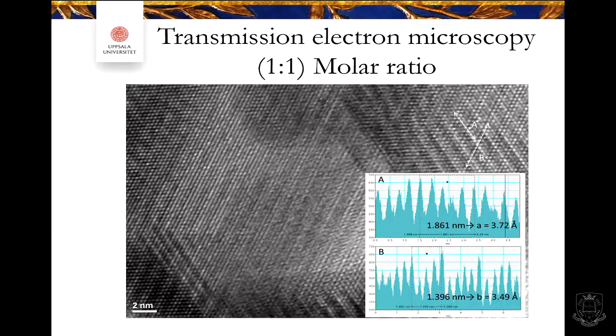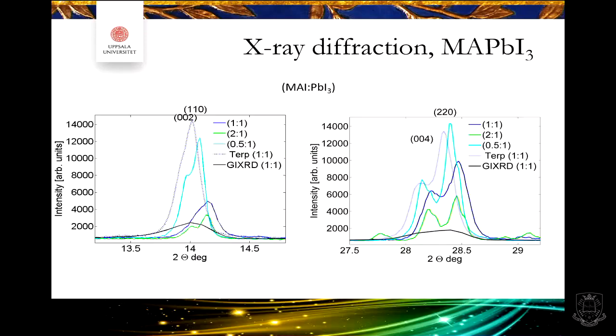This was also in the beginning of my work, when I started with transmission electron microscopy. Here I tried to see at what distance the atomic layers are in the structure, and I tried to understand how they were formed. And now I will sometimes use this expression. So this is a molar ratio between the MAI solution, we can call it, or MAI, the methylammonium iodide, and the lead iodide. So I wanted to compare different concentrations of those two. If you fail, for instance, when you're scaling your amount, if you have a little bit of deviation, what is happening? But here I had rather large steps.